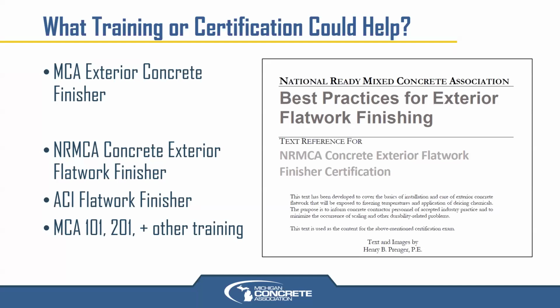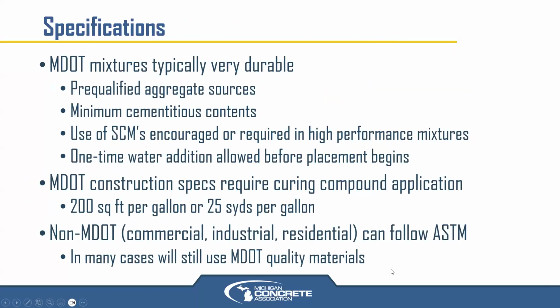When we look at the data, it seems that the mixes that are struggling are very lean mixes placed in areas that are more hand finishing. So it's taking a 3,500 curb mix and using it also for a driveway or a sidewalk where they're wetting it up and making it a higher slump. So if you're going to pour a little bit higher slump for driveways and sidewalks, make sure that you're using a 4,000 PSI plus mix. Yep. All right, let's finish up here, and we can still do some questions before we get to the full hour.